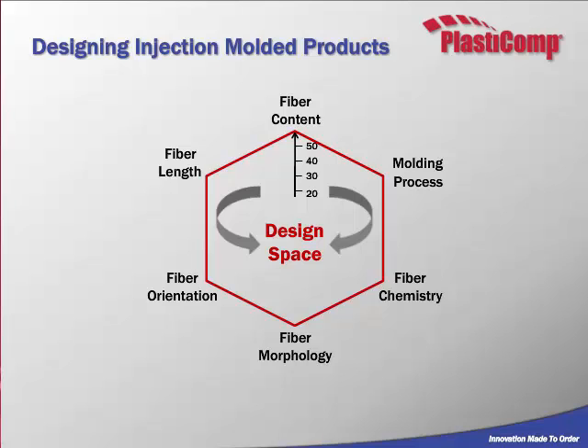All right, another way of viewing that is you want to think about your fiber content on top of that. We typically range from 20% to 50% fiber content. 20% will give you more strength than your virgin resin. And you really don't want to go above 50% typically because you start seeing a diminishing return on your strengths after that. It's also important to note that you're going to get a higher stiffness with the more fiber content that you have in the part.